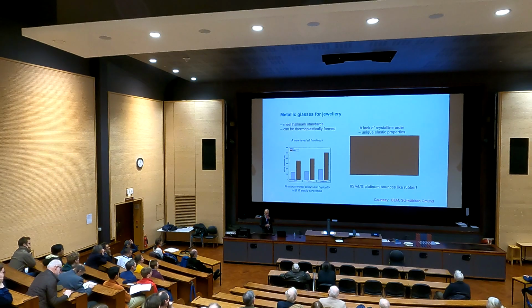and this shows a hallmark standard 85% platinum glass bouncing on the floor. It's a little platinum cage about 1 centimeter in diameter, and the sound wasn't working, unfortunately. But as it bounces on a ceramic tile floor, it sounds like a rubber ball bouncing, not a metallic ball, and that reflects the properties you saw earlier of this bouncing, where it has high yield stress but a rather low elastic modulus. So this is not yet widely available, but will be highly attractive for jewelry, because while you might not need the bouncing quality, you would certainly appreciate that it's very scratch resistant and the hardness is much higher than the crystalline metal counterparts.